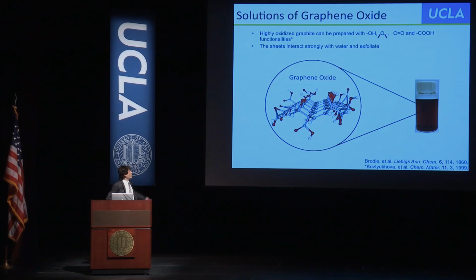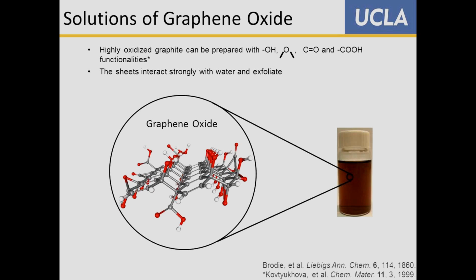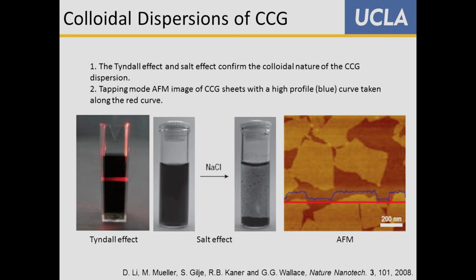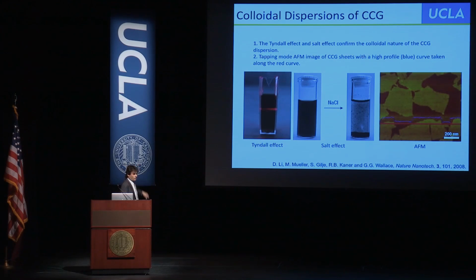Okay, first just a word about graphite oxide. So here's a layer of graphite that's been oxidized, disperses in water, and this chemistry goes back over 150 years. Well, when we picked it up, we looked anew at graphite oxide, and we find that when you reduce it with hydrazine, a good reducing agent, it forms a dispersion in water. I say it's a dispersion because if you look at the laser light going through, if it's a solution, the light goes through. But if it's a dispersion of nanoparticles, the light bounces off.